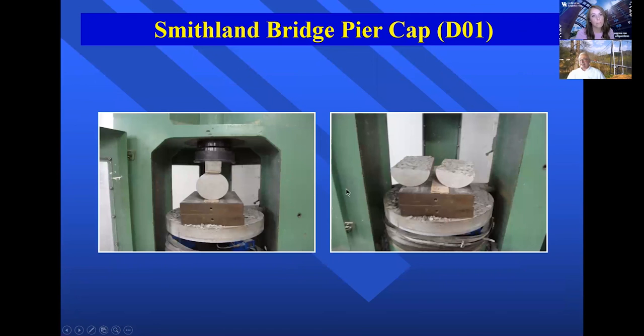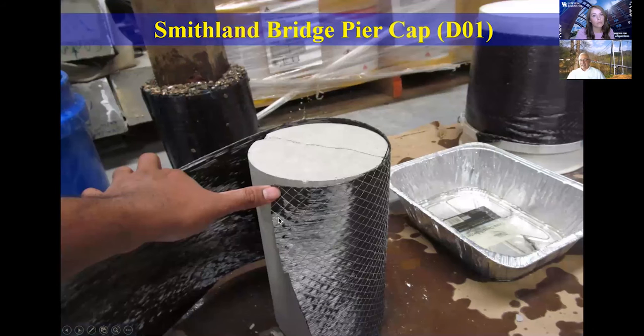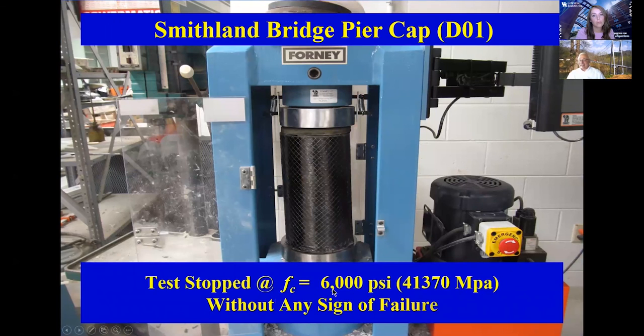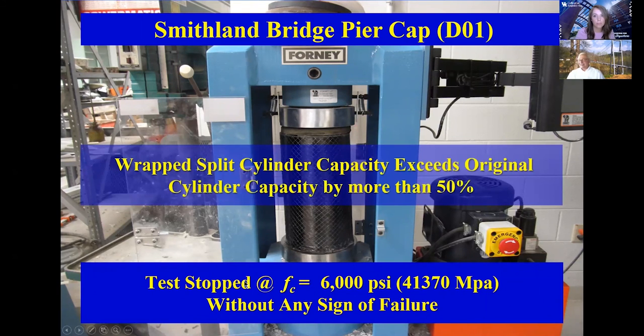if I take that cylinder and split it in half and wrap it with carbon fiber that we call CatStrong 120, so the cylinder is completely cracked in here. I stopped the testing at 6,000 because there were many students around us. Theoretically, this should have gone to 9,000. But at 9,000, it would have exploded like crazy, and they didn't want that. So it was 1.5 times stronger, at least, than the cylinder that was intact.